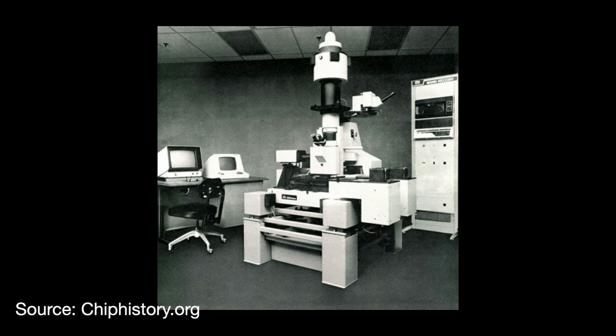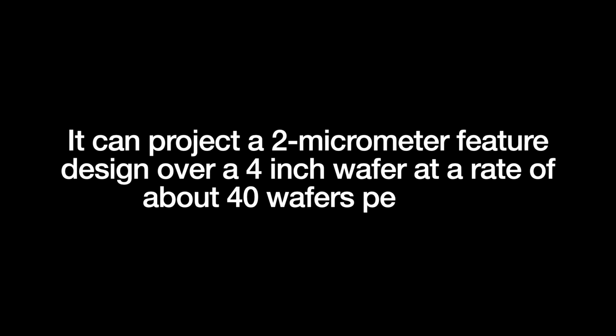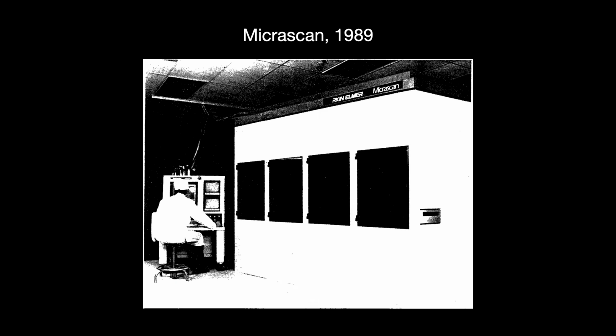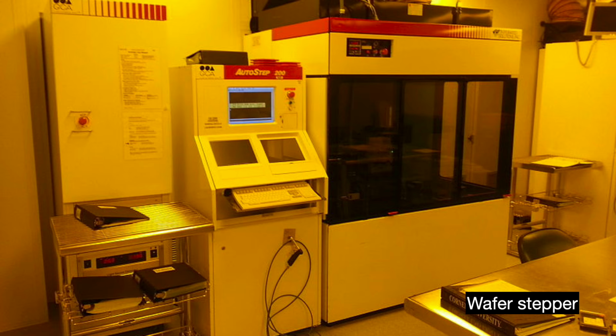The original Micralign worked beautifully. It can project a 2 micrometer feature design over a 4-inch wafer at a rate of about 40 wafers per hour. But its fatal flaw was that it projected one image from a mask across the whole wafer. When feature sizes shrank into the 1 micrometer range, semiconductor manufacturers required more detail and precision than this method can provide. Things got fuzzy. So GCA, Nikon, and Canon built on the aforementioned step and repeat cameras concepts to create the wafer stepper. Steppers fired small exposures across the whole wafer, trading speed and throughput for accuracy.